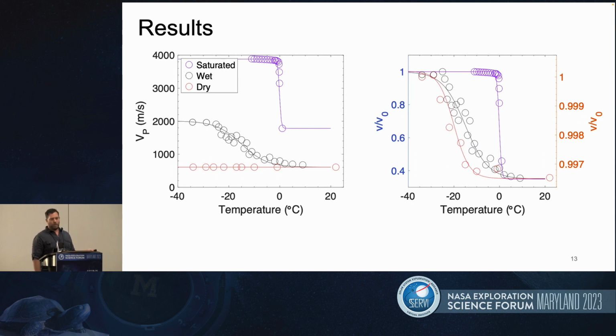And that's because the adsorbed water has slightly different properties than bulk water does, and it's harder to get it to freeze. And so when you have it strongly adsorbed, then you end up with this extended region of partially molten water at the grain boundaries that somewhere around -30 maybe seems to level off. We need to do these measurements to much colder temperatures, obviously. But this shows you the kind of behavior that we're looking at. And if you look at the dry sample, so that's a monolayer adsorbed sample, you see relatively little temperature dependence, but the other plot I have is the velocities normalized by their totally frozen velocity.